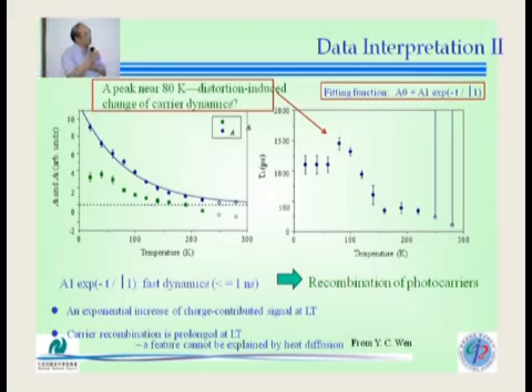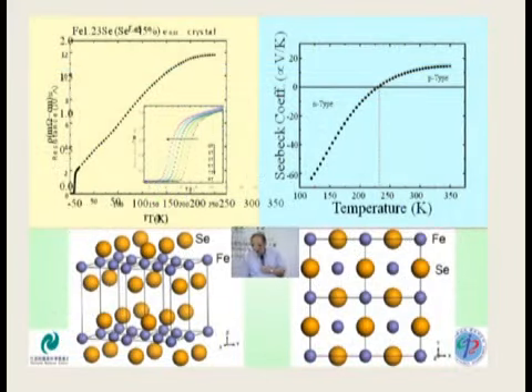So here is the message based on this. Apparently, a structure change at 100 Kelvin leads to many interesting electronic property changes, and also the spin part. And this really is the key to superconductivity. And it's not only for the iron selenide with the lower TC. Obviously for the other systems, we believe has the same feature.